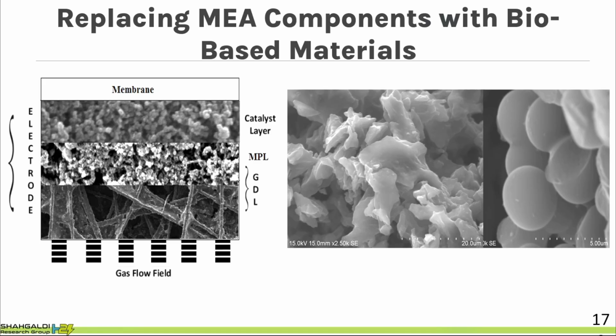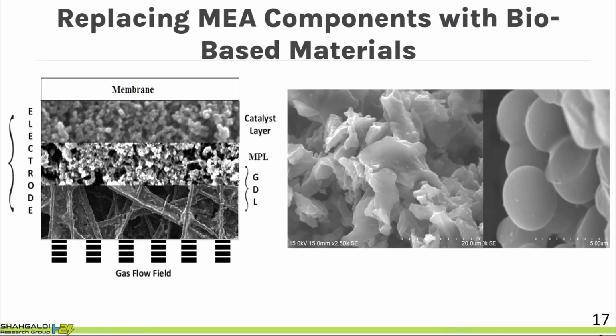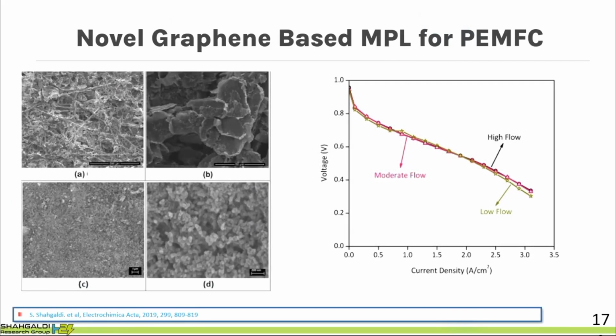So as you see here, we have the gas diffusion layer made of carbon nanofiber, the MPL made of carbon-based material, and then we have a catalyst support that is made from carbon-based material. A lot of carbon, yeah? So we want to be carbon-free, but there is a lot of carbon-based material inside the fuel cell. So one other work that we are doing in my research group is how we can replace this petroleum-based material with bio-based material. So these are the carbon materials that we produced in the lab, and we are applying them through the MPL, through the catalyst, and we got a good result. Hopefully you will see it; it's under publication. You will see the results soon.